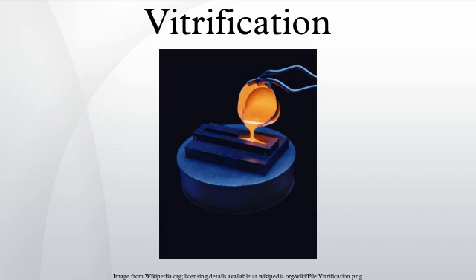In this context, zero porosity may be defined as less than 1% water absorption. However, various standard procedures define the conditions of water absorption. An example is by ASTM, who state the term vitreous generally signifies less than 0.5% absorption, except for floor and wall tile and low-voltage electrical insulators which are considered vitreous up to 3% water absorption.